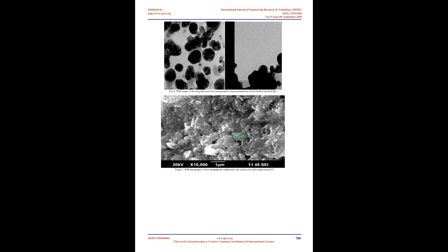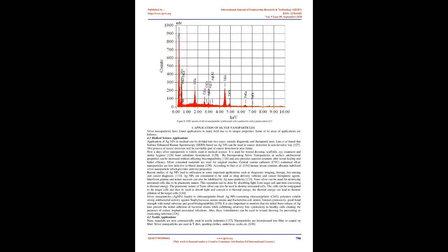Nersesian et al. 69 had prepared nanosized uniform silver powders and colloidal dispersions from AgNO3 by a chemical reduction method in the presence of sodium dodecyl sulfate as a surfactant. Wang et al. 70 have discussed producing AgNPs from silver nitrate and glucose as a reducing agent in presence of polyvinyl pyrrolidone, PVP, solution, whereas NaOH was used to enhance the reaction rate. Radziuk et al. 71 prepared AgNPs by reduction of silver nitrate in an excess of aqueous sodium borohydride, which was used as a reducing agent. The nanoparticles with a diameter of 20 nanometers are obtained.